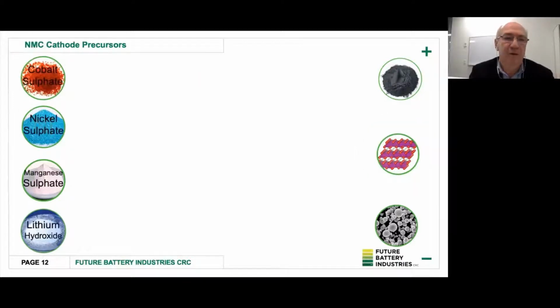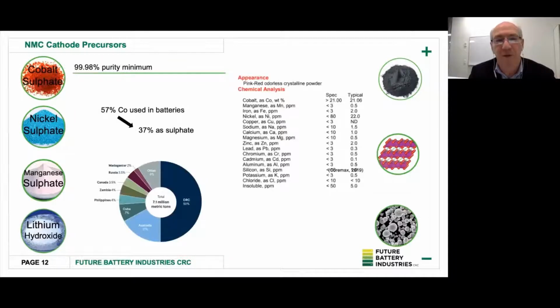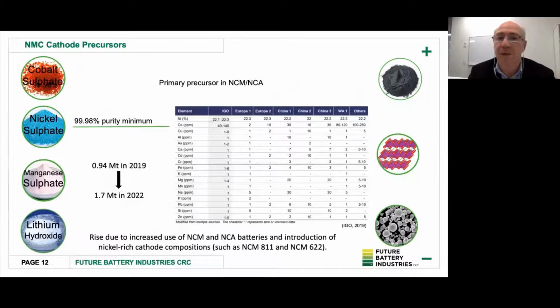And if we look at what sort of precursors we need to develop, they're typically, in this case, sulfate precursors. So cobalt sulfate, nickel, manganese, and the lithium is in the form of a hydroxide. The purities that we need for these materials are around 99.98%. So cobalt, for example, around 57% of cobalt used in batteries, and its form is 37% as sulfate. Australia is the second largest producer of this material. Nickel is the primary precursor in NCM, and it's increasing significantly in its introduction into the nickel-rich cathode compositions.